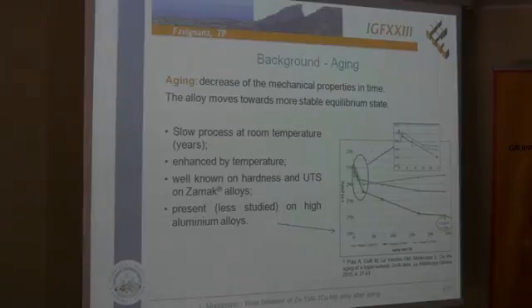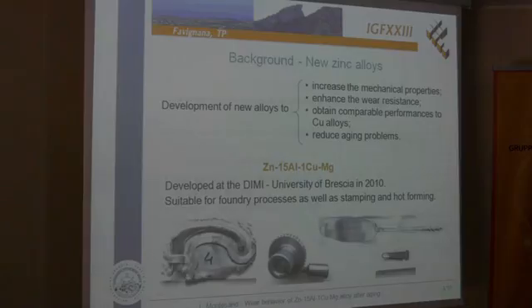The process is slow at room temperature. It takes years. We can say that the material reaches a stable condition after 20 or 30 years. But the process is enhanced by temperature, and considering the melting temperature of zinc alloys, 100 degrees is often sufficient to reduce the aging time from years to hours or days. The phenomenon is present also for high aluminum zinc alloys, not the traditional ones, but it is less studied. In the picture, I show you one of the studies of the aging phenomenon of this zinc alloy.